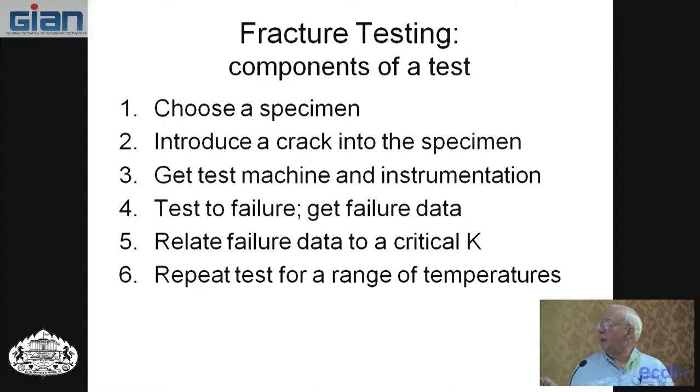Here are some of the steps then. You would choose a specimen, introduce a crack by fatigue pre-cracking, go to a test machine and get instrumentation, test it to failure or some point, and relate then that to a critical K, and maybe repeat that for a range of temperatures. So I want to go through each one of these.